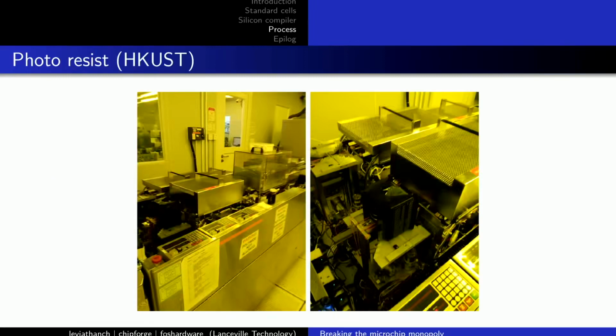So we have here an SVG coater. This baby dispenses HPR 500, a resist, automatically. We just have to put in the left, you see the cassette slot, like 25 wafers or so. Then you have a receive slot and put another cassette there. It just starts sucking in the wafers one by one, puts primer on it, soft bakes it, easy. Then you expose it, develop it, hard bake it, chill it.